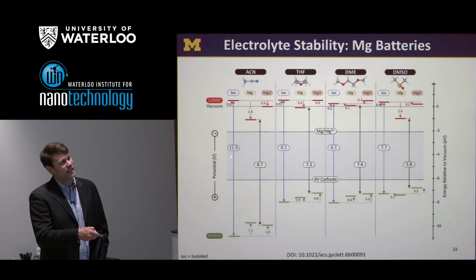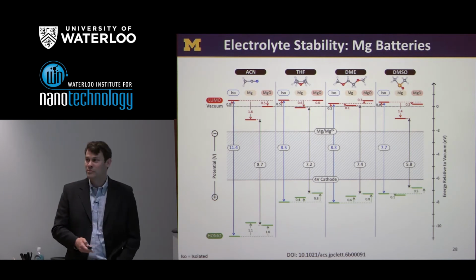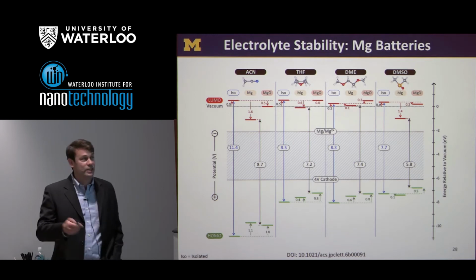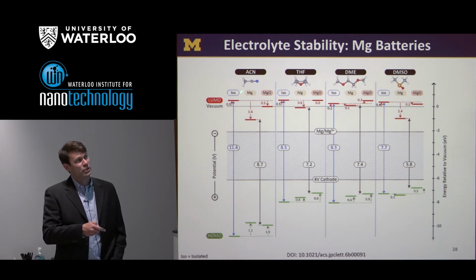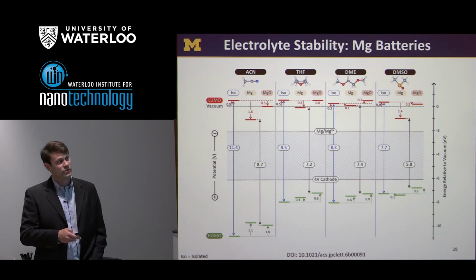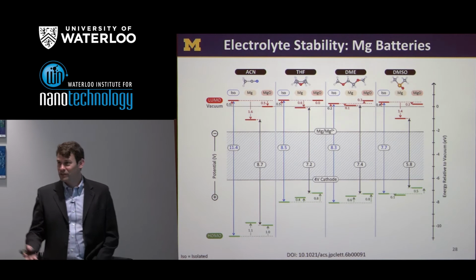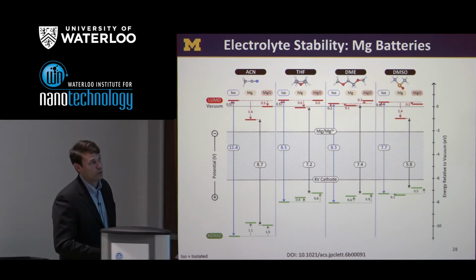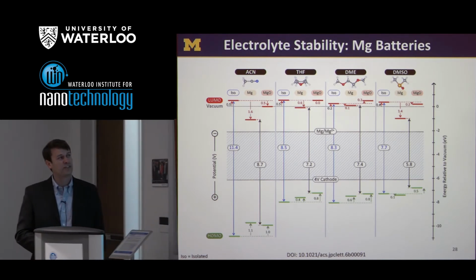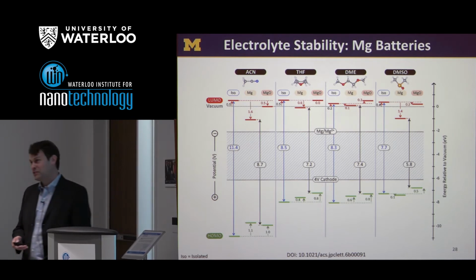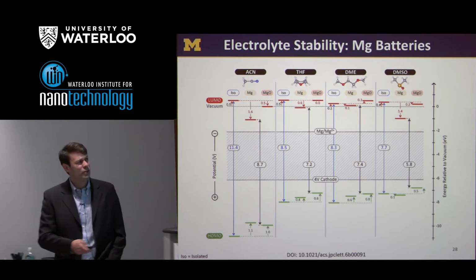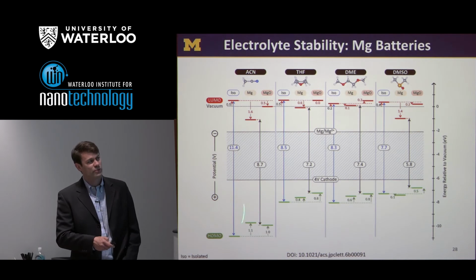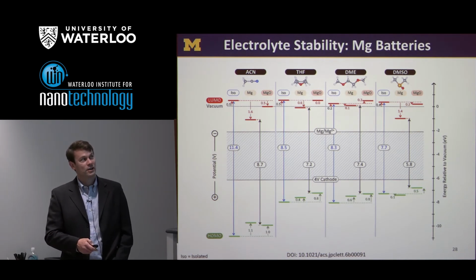So for example, if I take acetonitrile as an isolated molecule, it has a huge band gap or HOMO-LUMO gap of about 11 volts, or 11 eV in this case. When I take that molecule and put it on a magnesium surface, the LUMO shifts down by about 1.6 volts. So this indicates what we call renormalization of the HOMO-LUMO levels due to interfacial interactions. And so this is something which is, I'd say, an important consideration that one would look into after first screening for molecules that are appropriate in their isolated environment.